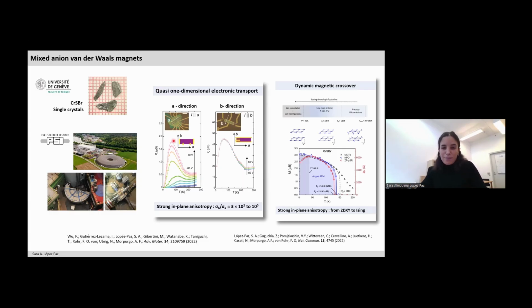was actually resulting in very anisotropic transport properties, which indeed opens up further functionalities, for example, to have independent transport along the in-plane directions. And in parallel, in our more conventional approach, we would also characterize how the presence of this strong uniaxial anisotropy in this material was driving complex dynamic correlations over a broad temperature range that we could unravel by combining complementary techniques.